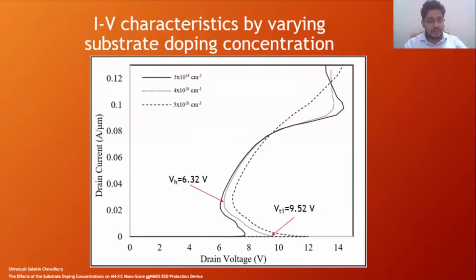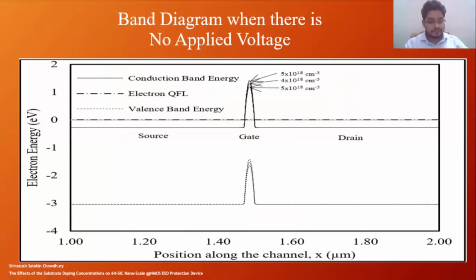As the substrate doping concentration is increased, the trigger and hold voltages are found to be 9.52 volts and 6.32 volts respectively. When the substrate doping concentration is further increased, the trigger and hold voltages increase to 11.99 volts and 6.89 volts respectively. This figure also shows that the turn-on resistance for the substrate doping concentration of 5E18 per cm cubed is the smallest among the results, resulting in better voltage clamping performance and improved current handling ability.